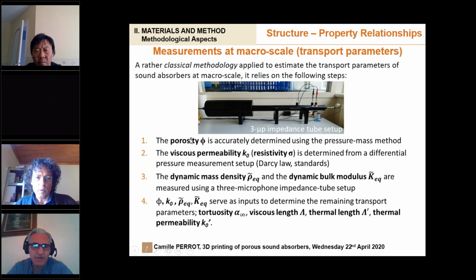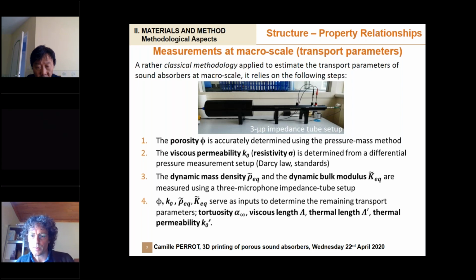Of course, a very important parameter is the porosity. And my experience is that you really need to try to get a very accurate measurement of porosity, because this is the first parameter you will be able to compare with your geometrical model. So if there is no agreement between these purely geometrical parameters which have been measured and computed, it will be difficult to get this link between microstructure and acoustical properties. Then you can measure directly the permeability or the resistivity from standard methods which are based on the Darcy law.